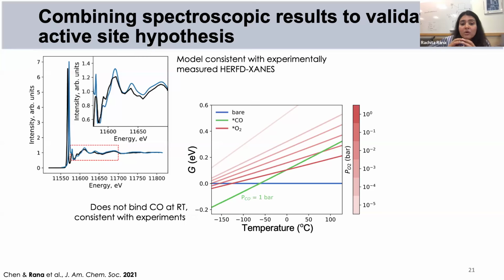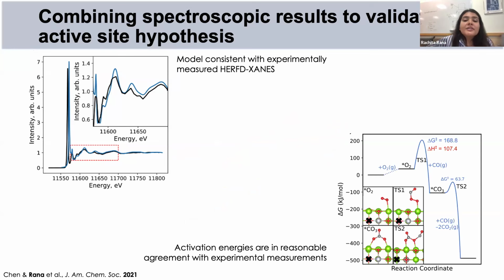In addition to that, we were also able to calculate binding energies of CO, because we did some infrared absorption spectroscopy measurements in the lab, and we found that this subsurface platinum was not binding CO. And what we see here from this plot is that at room temperature, all the CO is above 0.0 free energy, and so it's not going to bind CO. And we know that from both this result. The reason we were able to calculate this is because we had all the structures in the database and we could compare them. And ultimately, because we had an initial structure that we hypothesized was probably the representation of our catalytic site, we were able to calculate the barriers for a probe reaction. In this case, it was the CO oxidation reaction that we performed, and the results were in fairly decent agreement.